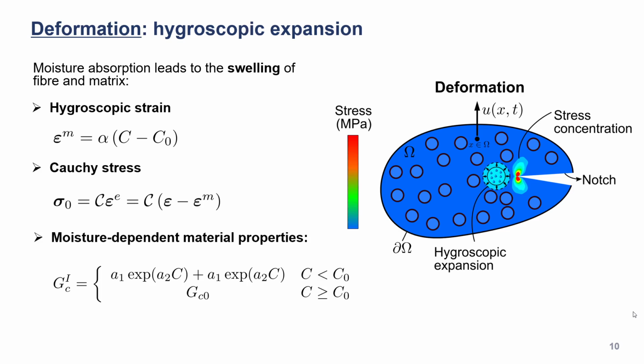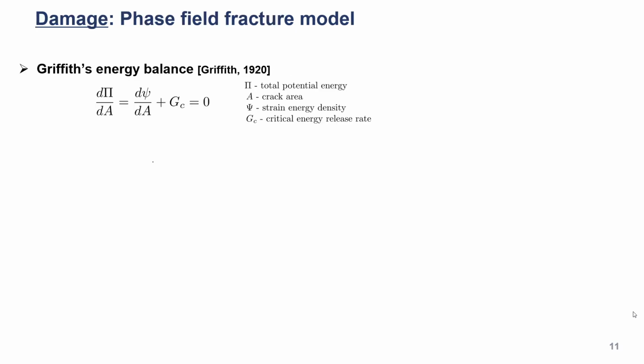In addition to that, we also need to consider the moisture influence on the material properties, such as on the fracture toughness, on the Young's modulus and strength. Once that happens, we can model the internal stress inside the materials. Then we can look at the fracture problems. We are using a phase field fracture model for this scenario.